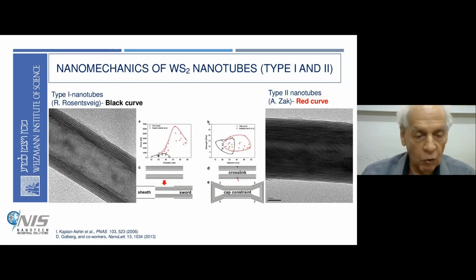They have a hollow core, and they fail like a sword in a sheath. Namely, all the load that we apply is actually taken by the outer layer, and they fail up to a force of about 6 gigapascal. So this is the mechanism that applies to this WS2 nanotube.